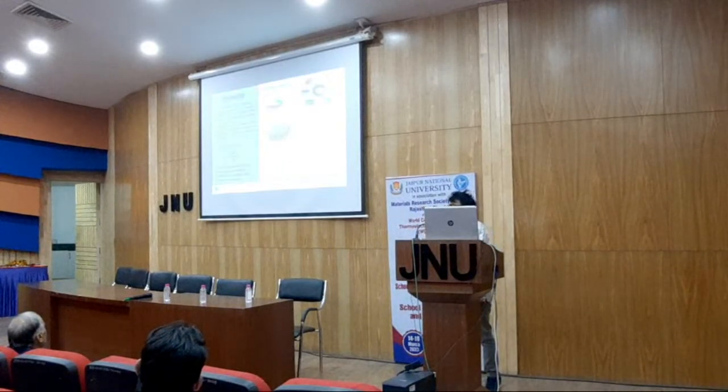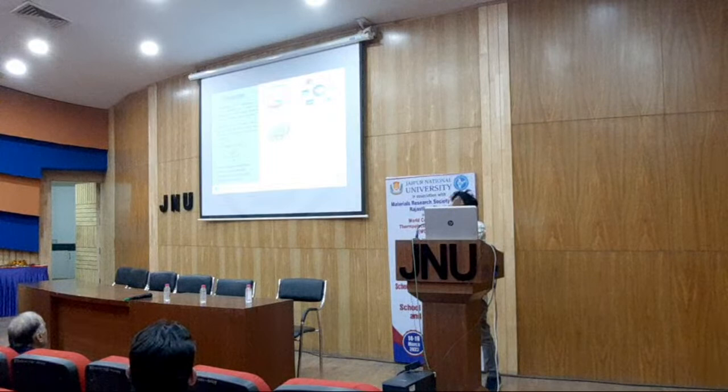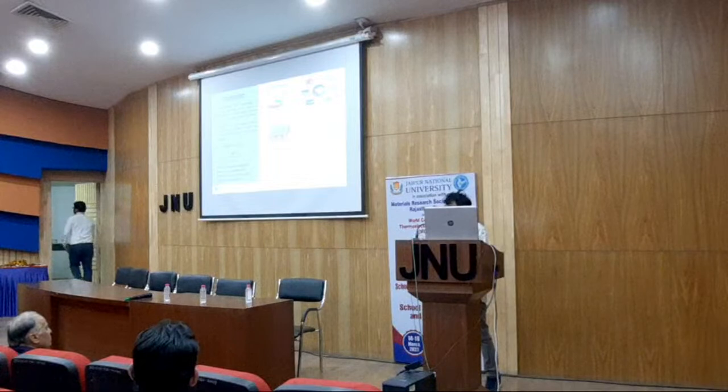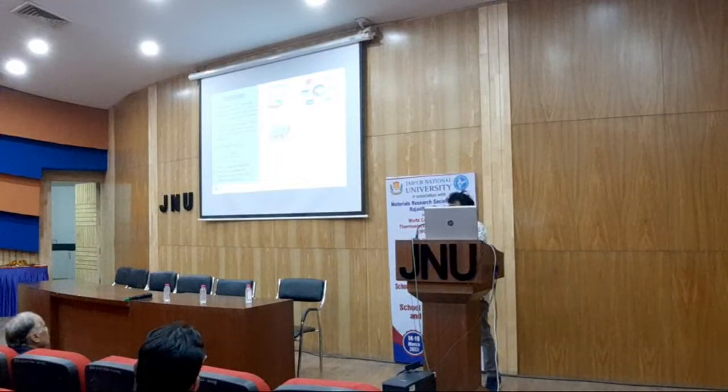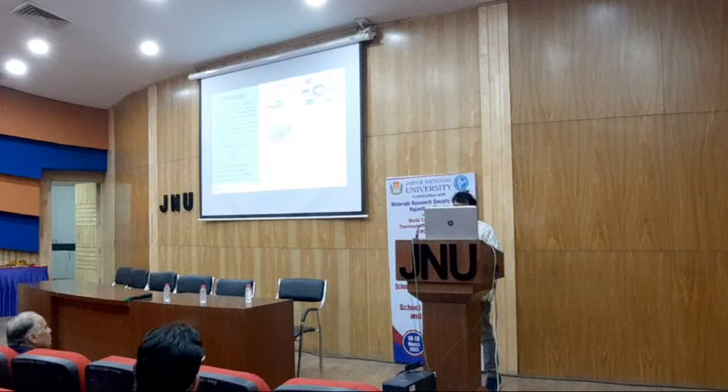The performance of a thermoelectric material is given by ZT. ZT is given by sigma S squared T by kappa, where sigma is electrical conductivity, how much electric current it can transfer in a material; S is the Seebeck coefficient, the change in voltage with respect to change in temperature; and kappa is thermal conductivity, how much heat it can conduct in a material. Our basic aim, what we researchers are trying to do, is to improve ZT by tuning all three properties using various strategies.